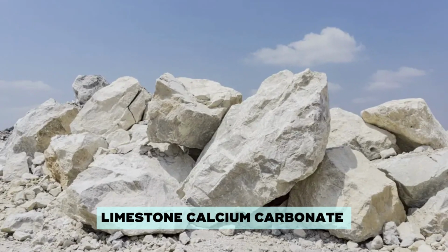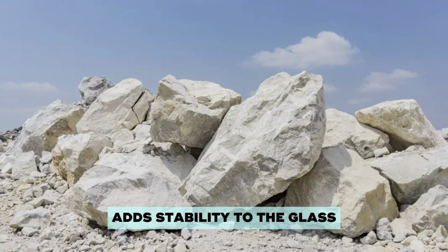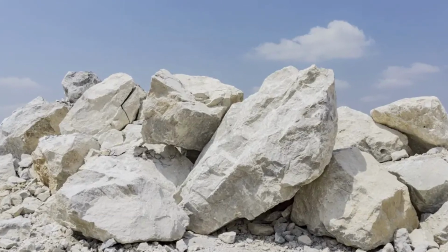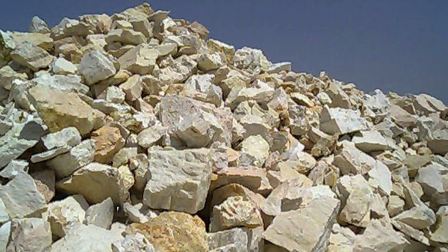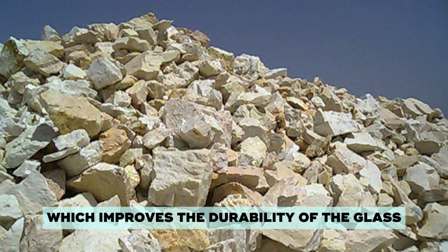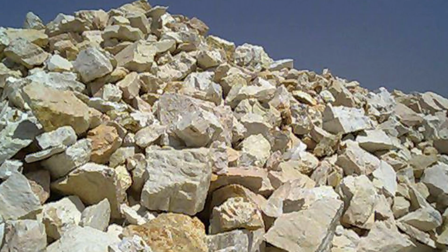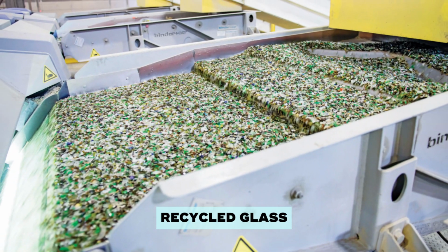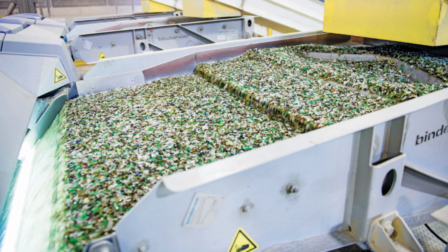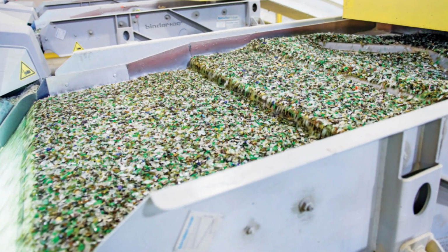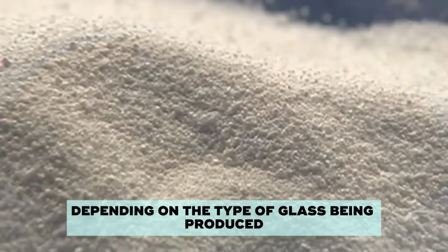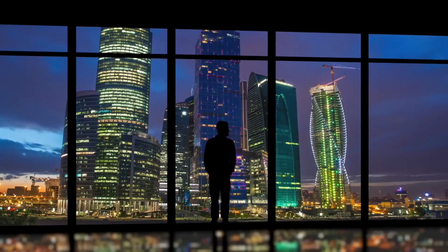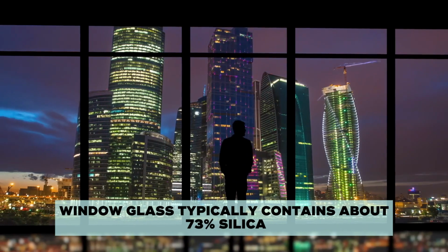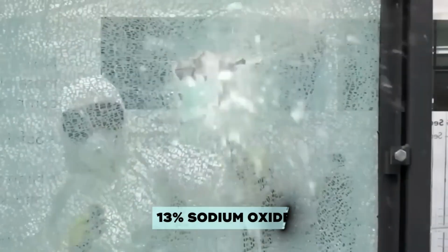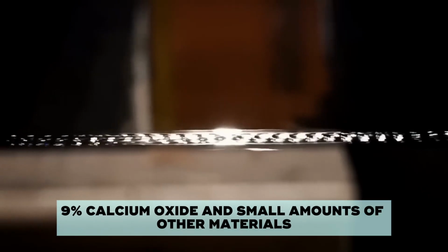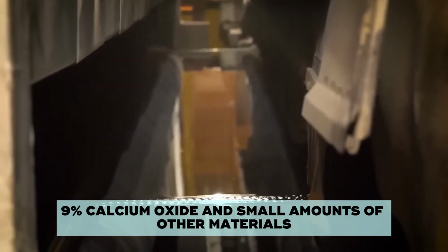Limestone, calcium carbonate, adds stability to the glass, preventing it from dissolving in water. Feldspar provides aluminum oxide, which improves the durability of the glass. Cullet, recycled glass, helps the raw materials melt at lower temperatures. The specific ratio of these ingredients varies depending on the type of glass being produced. For example, window glass typically contains about 73% silica, 13% sodium oxide, 9% calcium oxide, and small amounts of other materials.